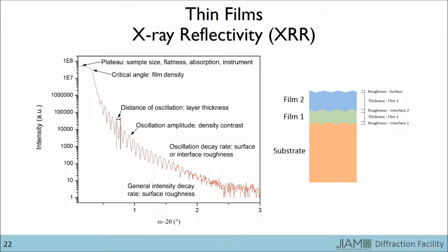A not-to-scale diagram of the type of sample that can be studied with this technique is shown on the right. The sample can have one film or multiple films on a substrate, but the roughness values must be less than about 2 nanometers, and the film thickness must be less than about 1,000 nanometers.